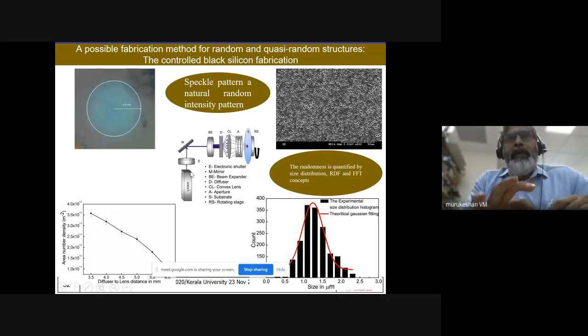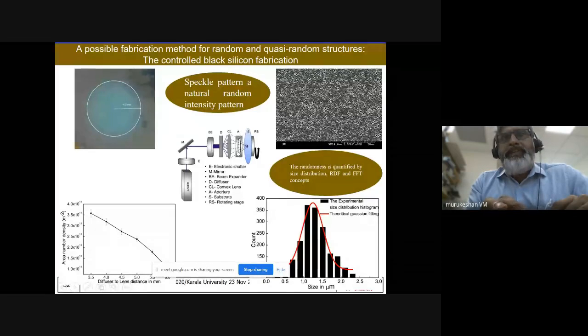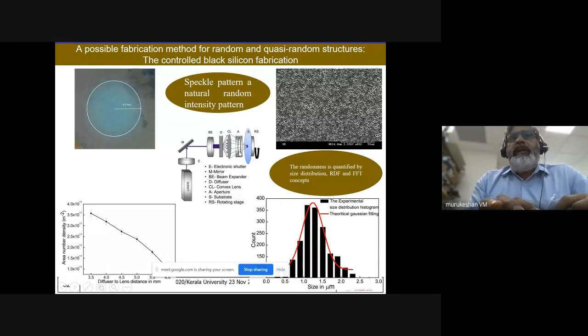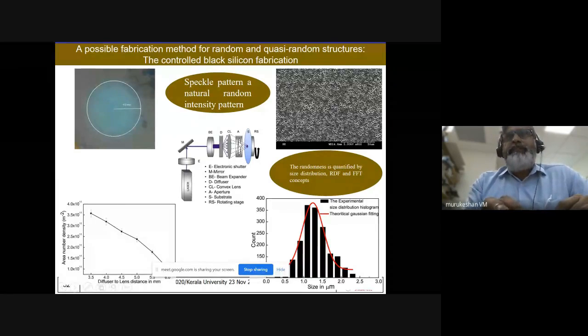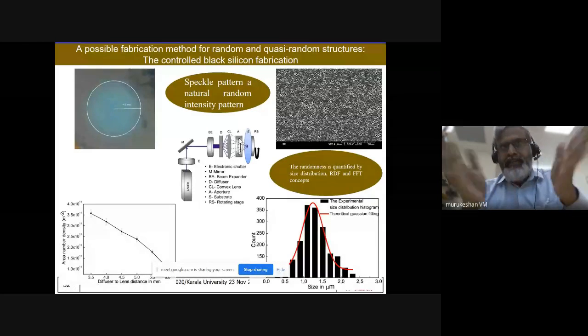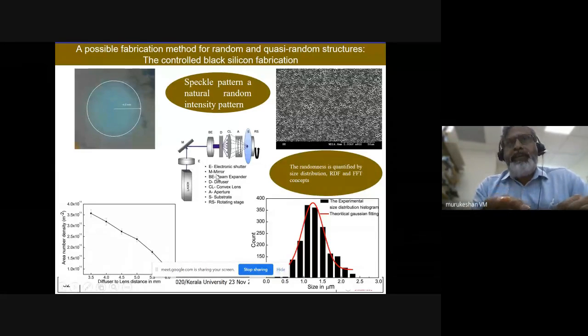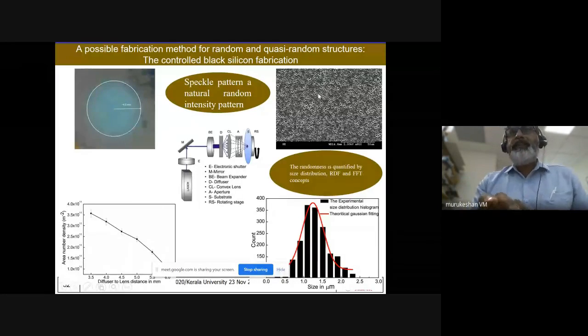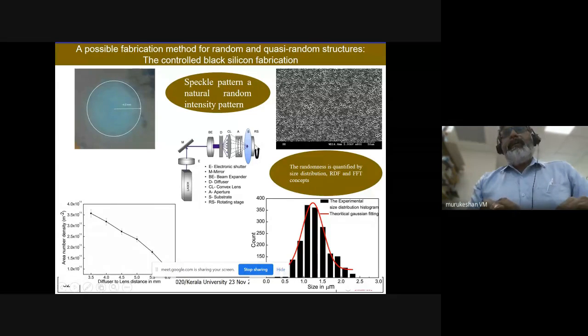This research staff of mine was very sincere in developing many different nice apertures. This is actually the major optical element, I would say. The aperture size we have defined based on certain simulations, and the distance between the D, CL, and aperture size has been varied. This is the simple configuration. You can see this is a normal laser beam that we used, and then we use this beam expander and the diffuser plate which generates the speckles. And the distance between the lens, the convex lens, and the aperture is going to give you patterns like this. These very random oriented patterns will be printed on this surface.